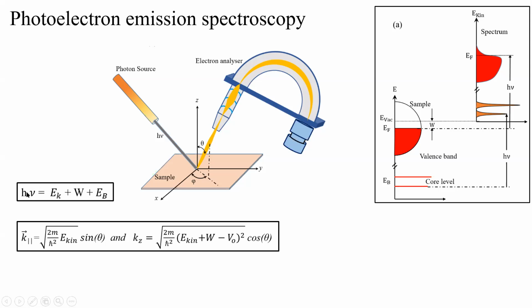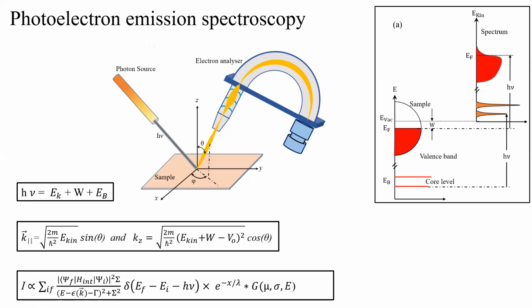And if you change the photon energy, you're basically changing the kinetic energy of the electron, and that means you are basically changing the kz. So by changing the photon energy, you can also change the kz momentum, and in that way you can get the whole Brillouin zone of the system. You can map the whole Fermi surface of the system.